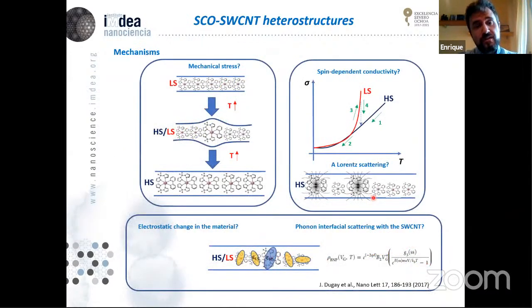So we were also wondering what could be the origin of this opening of the hysteresis, but also of these different conductances between high spin and low spin. We think that this could be of a mechanical origin. So the low spin molecules are smaller than the high spin ones. So this could induce different strain on the carbon nanotubes.